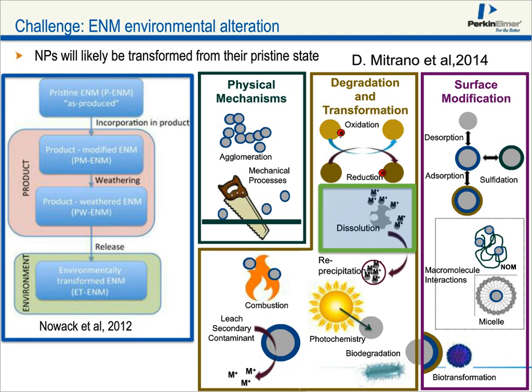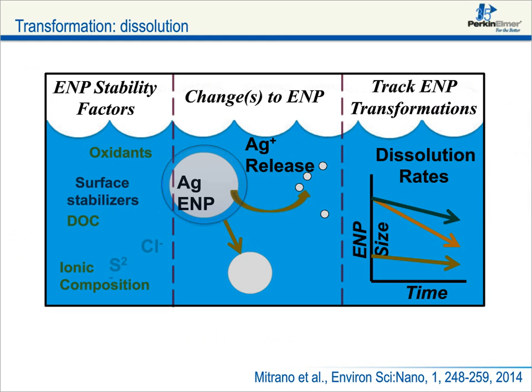In most cases, if we want to study the dissolution of a nanoparticle, say for example silver, one might focus on how environmental factors such as DOC and ionic composition affect this dissolution by trying to measure silver ion release. Well, in many cases, as Kevin pointed out, you don't see much silver ion. It's transformed into dissolved organic matter complexes or other things and can be lost. What we propose is to follow the changes in the nanoparticle, essentially the dissolution, the reduction in size, and from that we can mathematically calculate dissolution rates, again, by tracking the particle and not trying to track the ion.